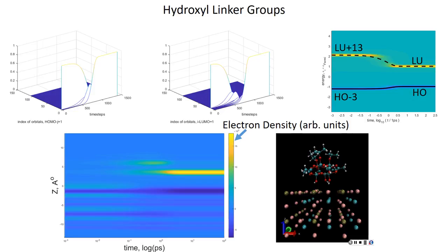You're showing one of these excitations from this table, right? Yeah. This is just the top one from the hydroxyl. Can you now analyze it and say where exactly you excite in this case? Is it the titanium dioxide quantum dot, the perovskite, or the hybrid state? This one starts out pretty much entirely localized on the perovskite. There's a little bit of electron smeared out all through here. So actually, before even reaching your lowest state, and before really going into the full time of your relaxation, you're already creating this charge transfer state.